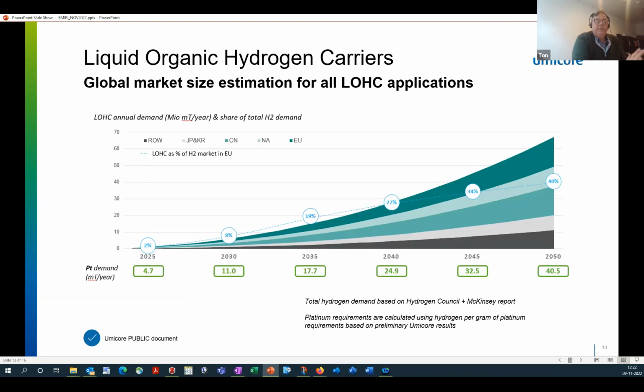But with these volumes, the other interesting part I want to draw attention to is it will require a certain amount of platinum. And the numbers we estimate is from what we have measured in the lab, how much platinum we need to produce a certain amount of hydrogen. And from that estimate, we come, if the technology grows to this level, that we need 30 to 40 tons of platinum per year. And that has to be seen in perspective of the total platinum production, which currently is 200 tons per year. So in that sense, this technology is potentially a large fraction of the noble metal usage in the world.